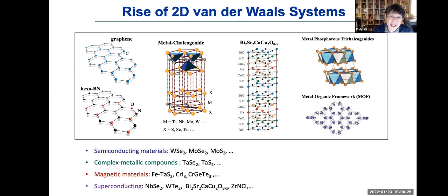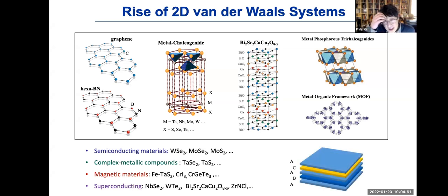Perhaps the most exciting opportunity beyond this diversity is that, because of the weak van der Waals force holding them together, in principle you can put two different types of material together to make an interface between them without consideration of chemical incompatibility, which is usually a big issue when you create a heterostructure material. Hence, stacking these materials in different sequences and with different functionality to come up with a quasi three-dimensional structure becomes one of the really exciting possibilities of this research field.